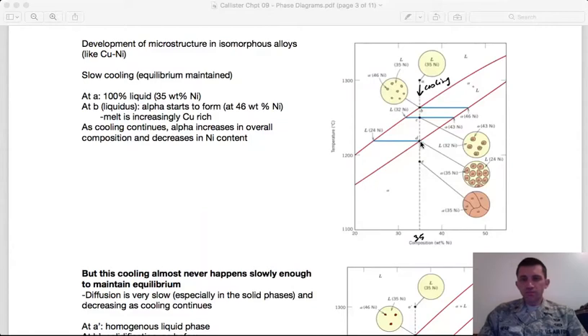Thirty-five percent nickel, the liquid is down to 24% nickel, and so at this point I've run out of melt, and by the time I get to point E, I have fully solidified alpha grains with a nominal overall composition of 35% nickel, which matches what I started with.